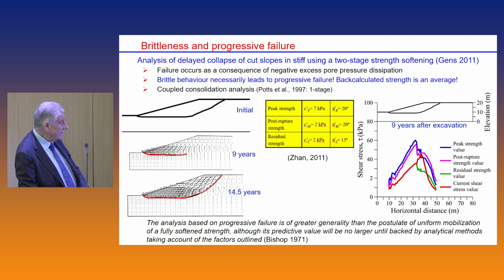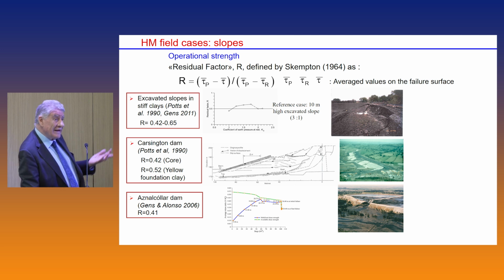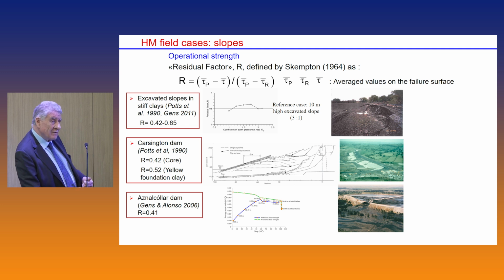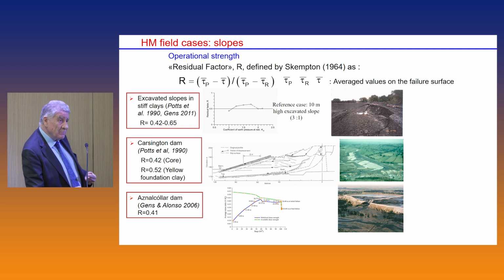And this is the evolution of the peak, post-peak and residual strength compared to the stresses which are applied, and you can see that there is a variety of strengths operating at any time. So that creates the question, not easy to answer: what is the operational strength? In a sense, what strength should I use for design? I don't think we can give a single criterion, for the reason that this average must depend on the geometry of the problem, on the scale, on the brittleness, on the rate of degradation of the brittleness. All these factors must play a role. So it's unlikely that a single size fits all.